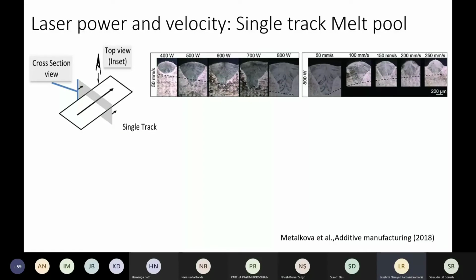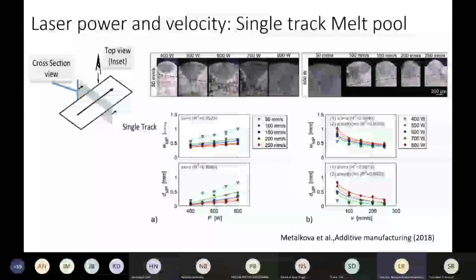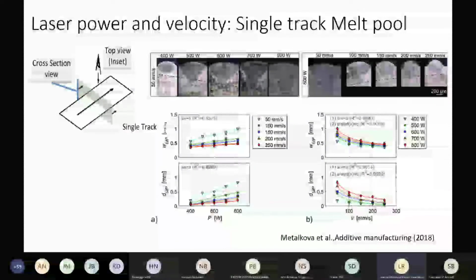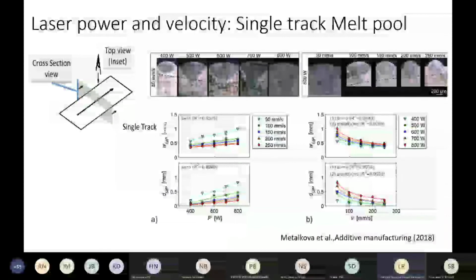Now the shape of this melt pool, you can obviously see it changes when you change the power and it changes when you change the speed. Either of these parameters changes the shape and the aspect ratio of the melt pool. And a lot of studies have focused on this aspect. They look at the width and the depth, essentially the aspect ratio of the melt pool, and then they've seen that it increases or decreases depending on the speed as well as the power of the laser.